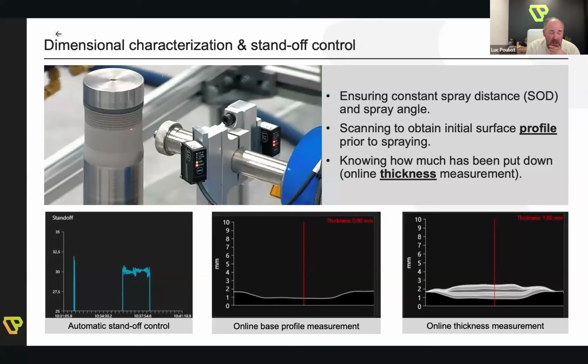What else? Well, everyone who has operated a cold spray booth eventually has to measure what's being deposited. So you have to stop, wait for cool down, get in, and use calipers or other means to determine how much material has been put down. So we have developed a relatively simple approach to scan the area that needs to be coated or repaired, and that would be the central picture, basically the base profile measurement. And every 2 or 3 or 4 passes, depending on what the operator wants, you can quickly scan again, and you eventually obtain the right-hand side graph that shows you how much material has been put down, and then eventually you have enough to go to machining.